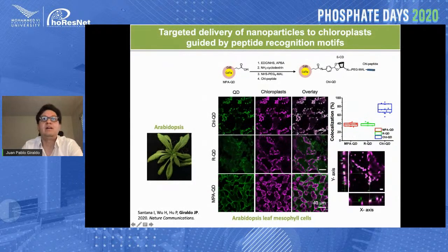And so how does that work? We have used fundamental research, and we have focused on Arabidopsis plants because we understand their molecular biology very well. And we have also used quantum dots that are made with cadmium and telluride because they allow us to both track the fluorescence of the particles in the plants and also detect them by other advanced analytical tools, as I showed you, like elemental analysis and others. And with that, you can see here that the quantum dots coated with this chloroplast targeting peptide, shown here in green, co-localize very well with the chloroplasts shown here in magenta. This is a high level of co-localization that we have not seen before.